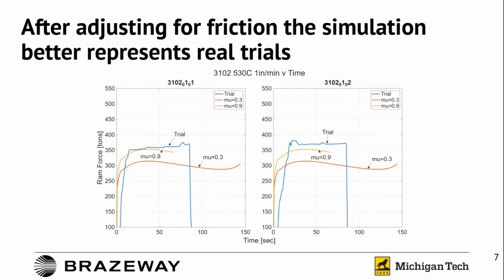So after obtaining thermo-mechanical data from hot isothermal testing or Gleeble testing, we were able to develop material parameters that were used in Inspire Extrude simulations. We then decided to validate that model with a real-life extrusion trial. We did find out that friction does play a large role in our simulation, as our extrusion ratio is extremely high at 225. So we did have to adjust our friction coefficients, but that does give us a better correlation to real life.